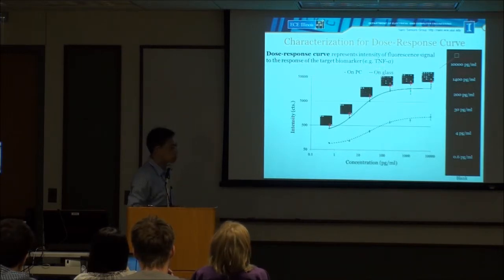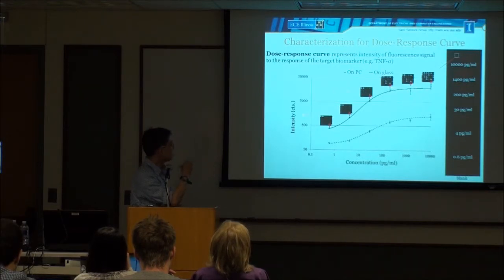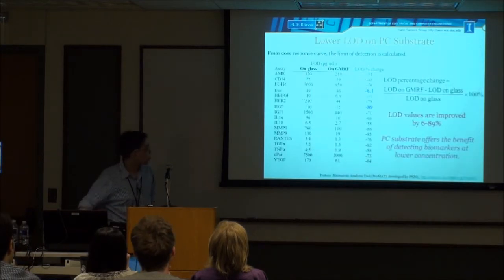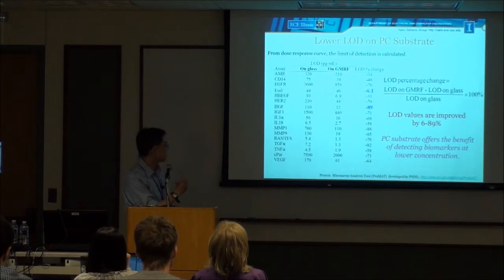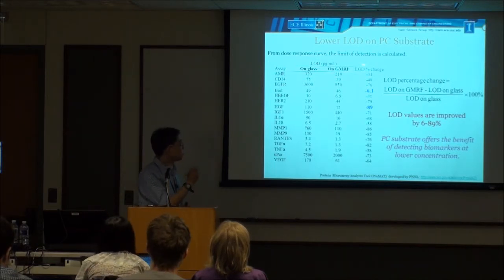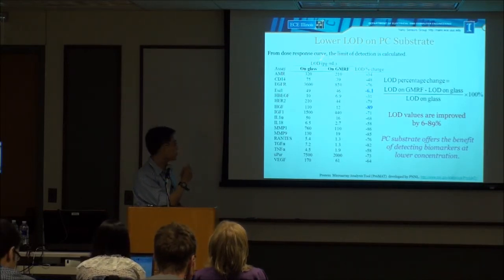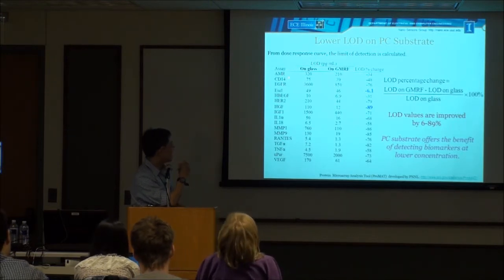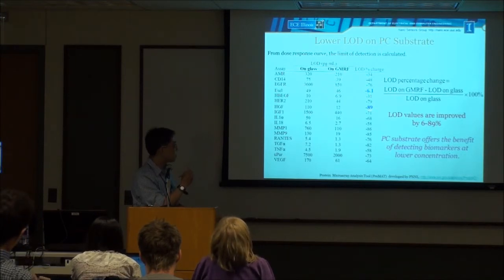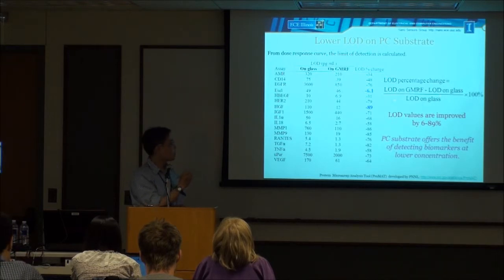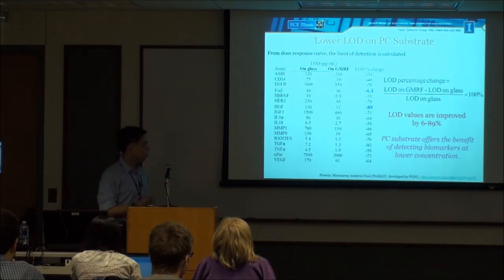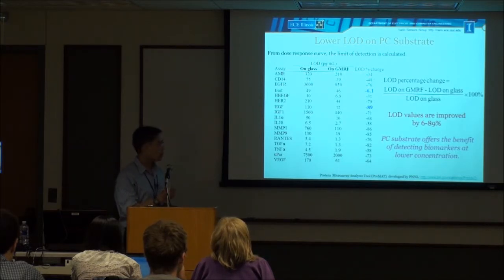This figure shows the dose response curve. Each spot means one concentration. On the photonic crystal substrate, you can see the intensity of fluorescence is much stronger than on glass substrate. We analyzed the dose response curve using free software from PNNL called Protein Microarray Analysis Tool, which can help calculate the limit of detection from the dose response curve. Among those different assays, we found the highest improvement is 89%. The improvement was calculated as the difference of the limit of detection on photonic crystal substrate and on glass substrate, divided by the limit of detection on glass substrate. This table tells us the photonic crystal substrate offered the benefit of detecting biomarkers at much lower concentration.